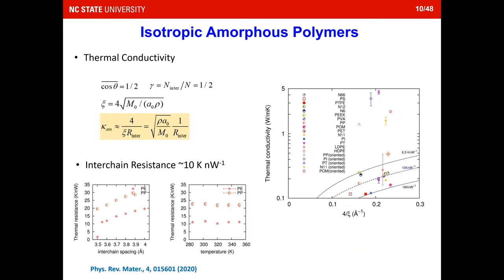If we apply this first to the isotropic amorphous polymers, then it will be much easier because it's isotropic. You have a lot of assumptions to work with. You come up with very simple equations related to the mass of the polymer monomer and the bonding length, and then the interchain transfer resistance. My PhD students actually used molecular dynamics to calculate the interchain resistance and found it's on the order of 10 Kelvin per nanowatt. And if we apply that value and fit it to the experimental values of all kinds of polymers, you find that it's actually pretty consistent.